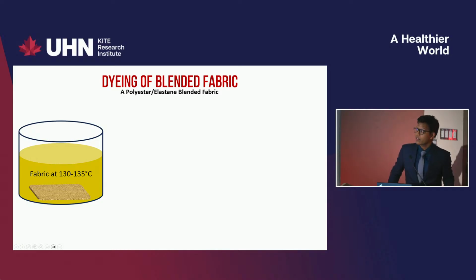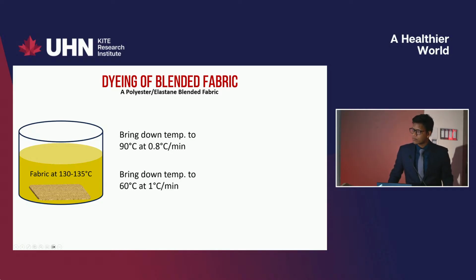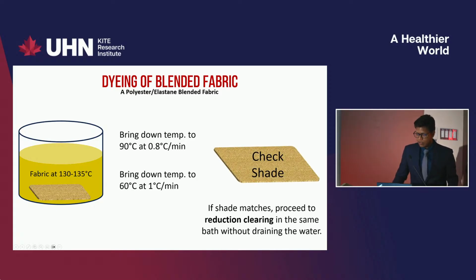At 135 degrees centigrade temperature, the dyes are already inside the fiber. But now we need to close the fiber so that the dyes don't come out. So we start cooling down the temperature. When we start cooling down the temperature, the polyester again comes into its original shape, and the dyes remain inside of the fiber itself. So we start bringing down the temperature. At first, we bring it down to 90, and then we bring it down to 60 degrees centigrade temperature. And then we check the shade.